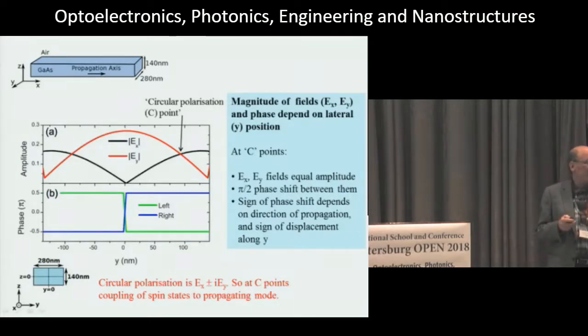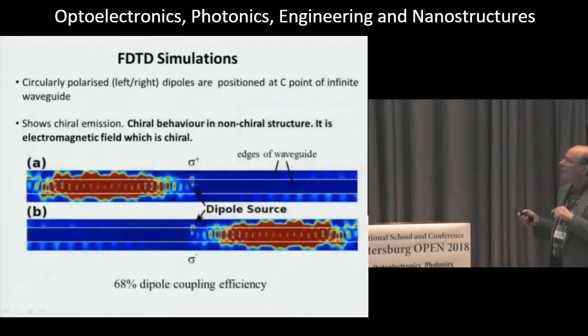So in the nanophotonic geometry, we support circular polarization. And so at the C points, we have coupling of the spin states to the propagating mode. And these are electromagnetic simulations, so finite difference time domain simulations. So we put a sigma plus dipole at this point, at the C point, at the circular polarization point, and a sigma minus dipole at the same point. And what you see is that the sigma plus dipole propagates to the left, and the sigma minus dipole propagates to the right. So the simulations tell us that we can indeed transmit spin information in the nanophotonic geometry.